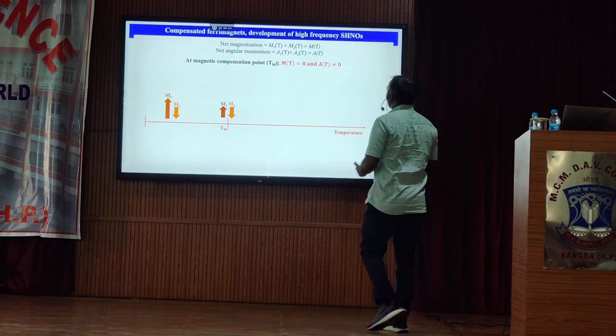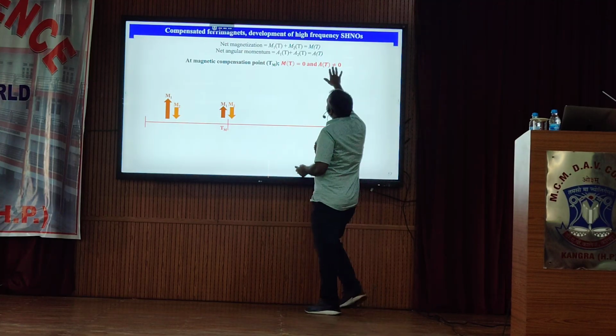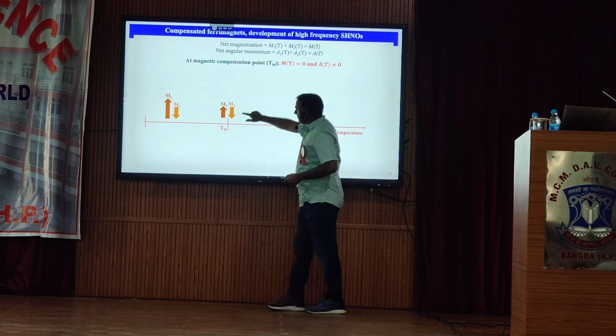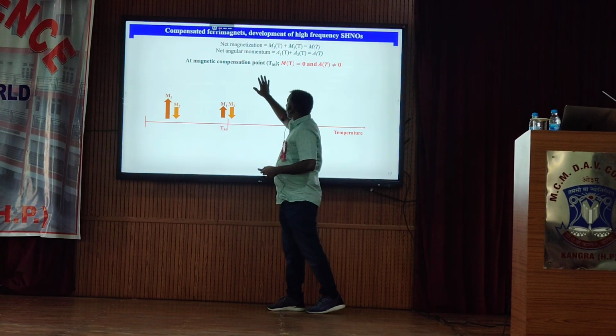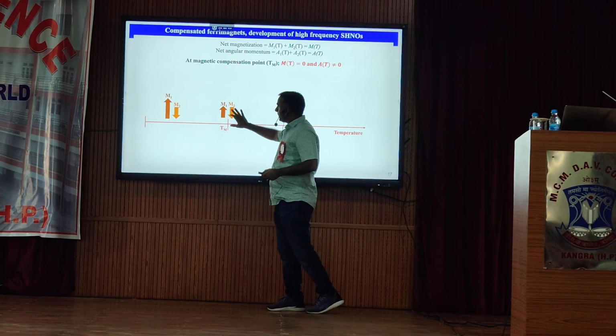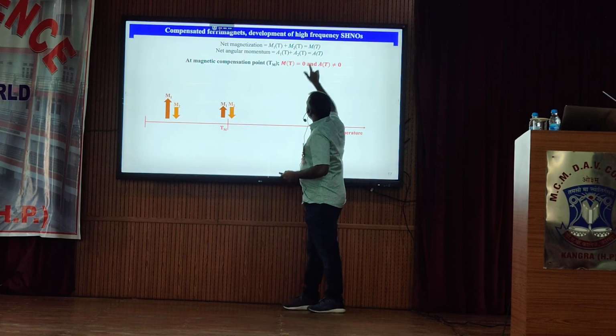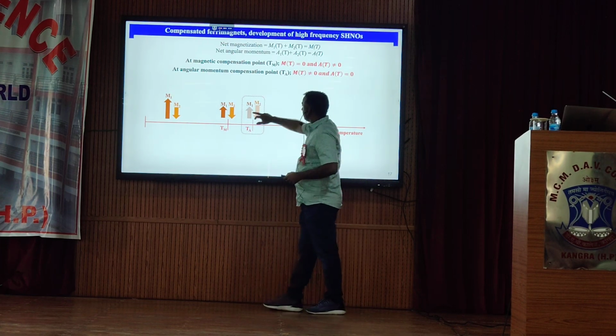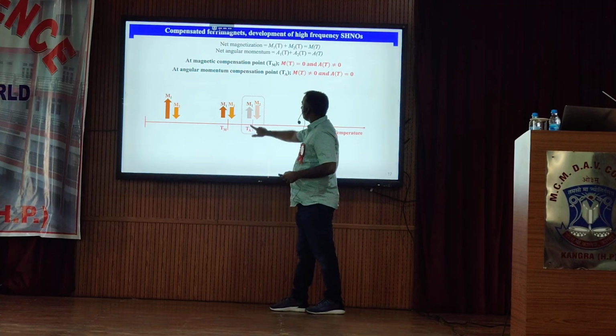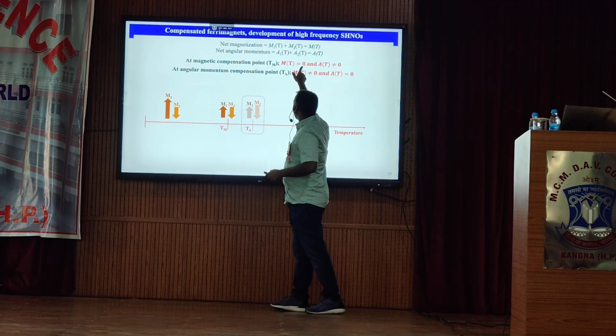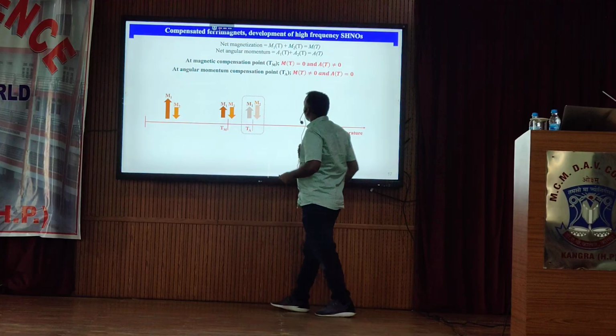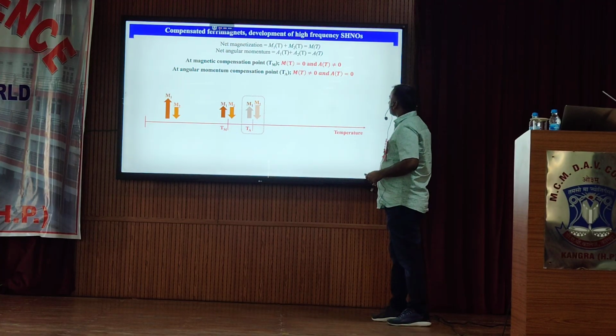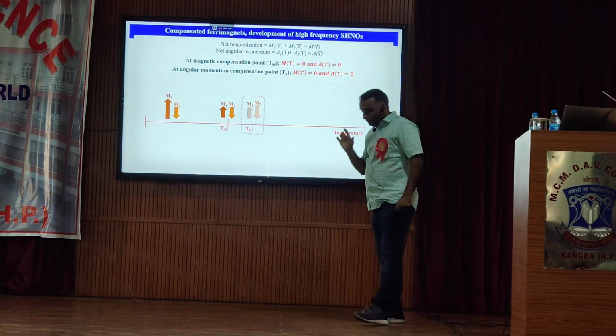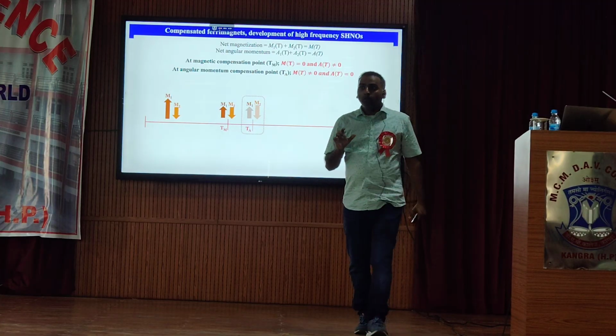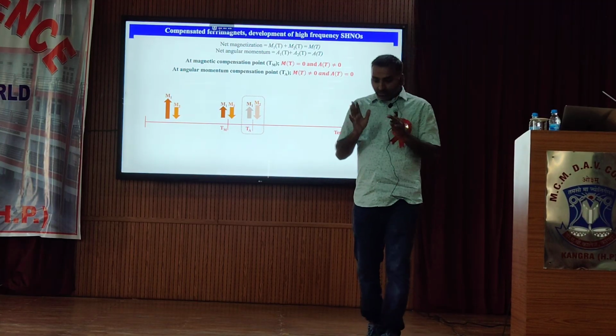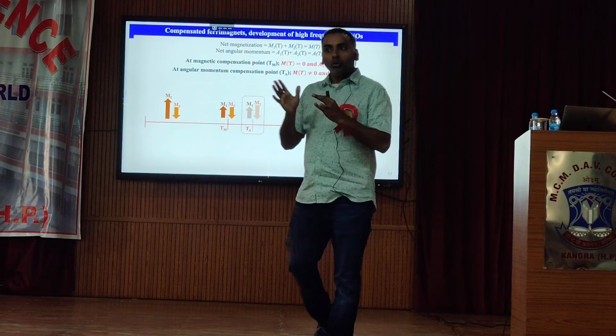We want the net angular momentum to compensate, which happens at the angular momentum compensation point. At this point, when they are equal, the net is 0. So we are interested in being near this point, where the net angular momentum is 0 but there is non-vanishing net magnetization. This kind of point, where the two magnetic sublattices almost cancel but not completely, can be reached not only by changing the temperature, but also by tuning the composition.